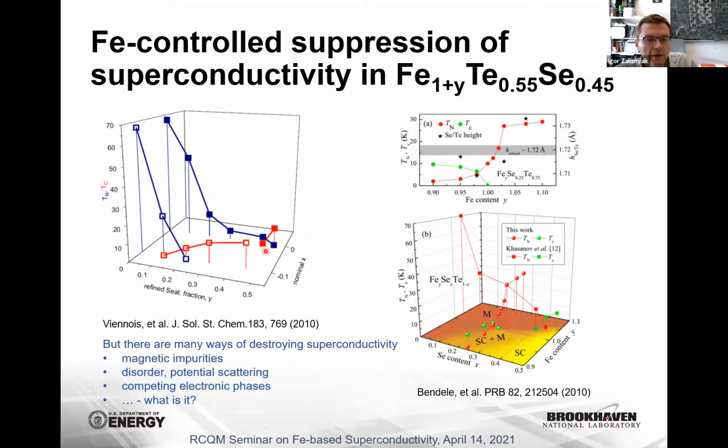that in order to have a well-developed bulk superconductivity at compositions between 0.3 and 0.5 selenium doping, you need an iron deficient material. For nearly nominal iron content, even for selenium doping of 0.45, the material can be non-superconducting. So iron represents a substantial handle on the appearance or disappearance of superconductivity in the material.